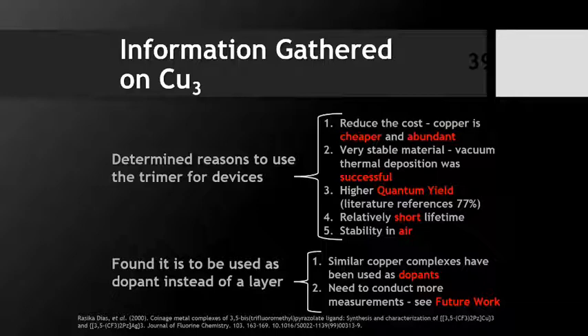We found out that we could use it, most likely, in our devices, because it would reduce the cost, as Dr. Omary talked about quite extensively. Copper is a cheaper and more abundant metal than, say, iridium or platinum. It's a very stable material. We actually successfully vacuum deposited this material in our deposition device onto substrate, so we know it's a very stable material. It has a high quantum yield.